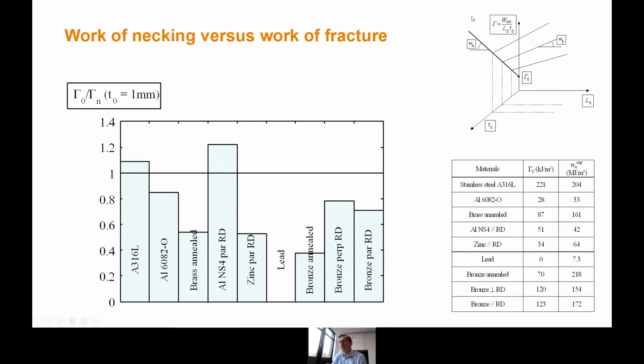We measured using this double separation of energy contribution. We estimated experimentally the gamma 0 for all these materials and the work of necking per unit volume or per unit area. So in this case, what you see is the ratio between the damage and fracture contribution divided by the necking contribution, both expressed in work per unit area. And then we have to take a specific thickness, because for each thickness you get a different work of necking. So we took 1 millimeter, typical sheet.